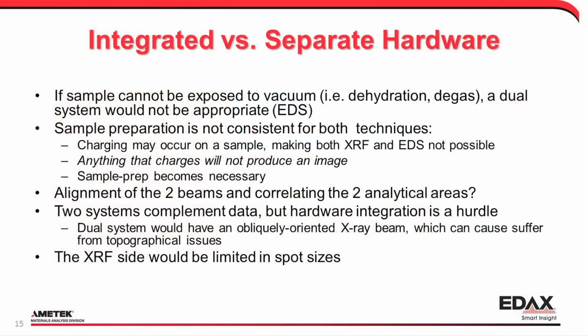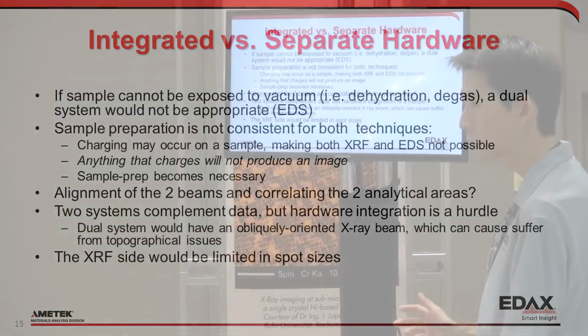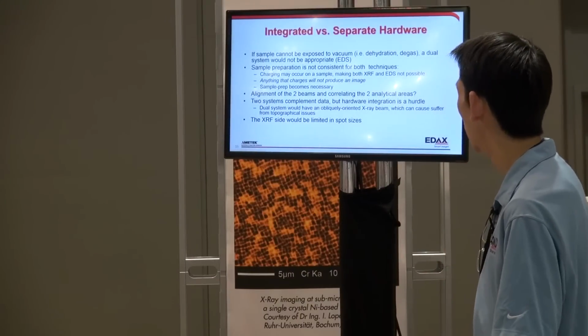Integrating the hardware together for both EDS and XRF, it is possible to do, and there are some issues with that. Yes, we're saying the data complements each other very well. However, if you start to integrate the two hardware together, you face an issue with, for one, sample type. If you can't pull vacuum on your sample, whether it's wet or it will degas, you can't run it on that system, period, due to the fact that you have an EDS chamber, obviously, that needs to be evacuated.